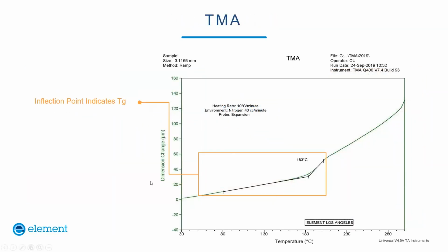Here's an example of a TMA curve. You can see that it's very linear here, and then it goes through a change, or an inflection point. And this happens at the glass transition temperature. This is a higher temperature material, so it's happening at 183 degrees C.